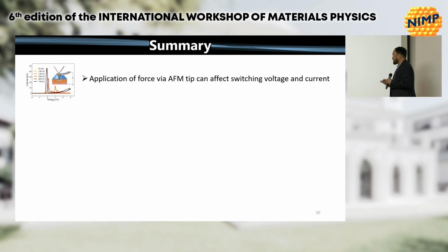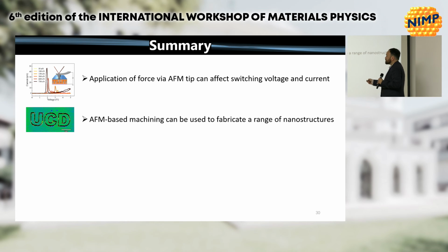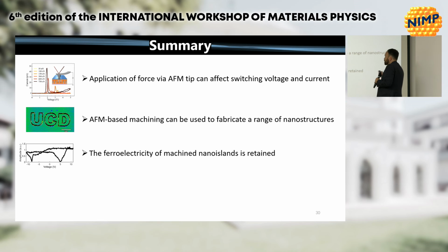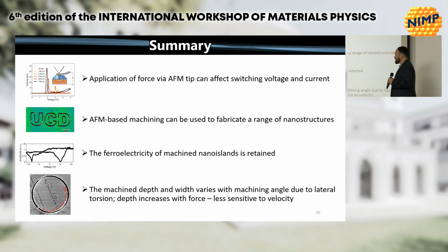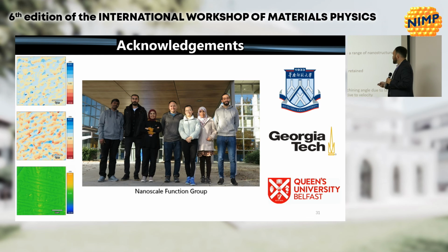So the basic summary here is that we can apply a force with an AFM tip to both image, to do regular PFM, and to induce a structural phase change through the application of the force. We can change the switching current. We can change the coercive field. We can do machining to make a variety of different structures. In ferroelectric films, you have to optimize it for the material that you're looking at. We were able to retain the ferroelectricity in these nanostructures that we carved, and the parameters can be checked by the same method that we used here.